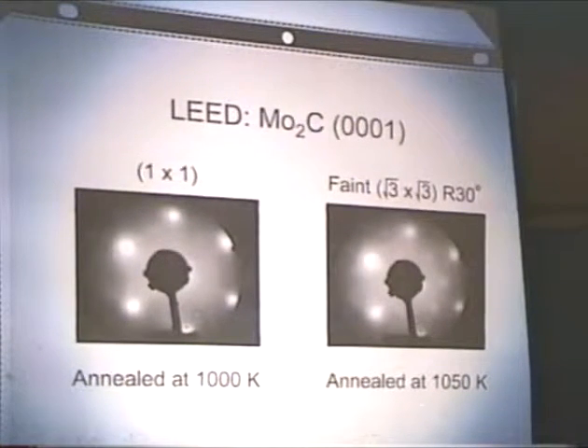However, annealing the same surface 50 Kelvin higher, which is where we begin to detect the iron contamination, we see a faint root 3 by root 3 rotated 30 degrees adsorbate structure. And again, this may or may not be due to the iron contamination. Once we have the new sample mounting procedure implemented, we'll be able to further investigate that.